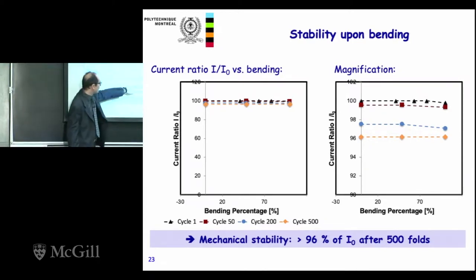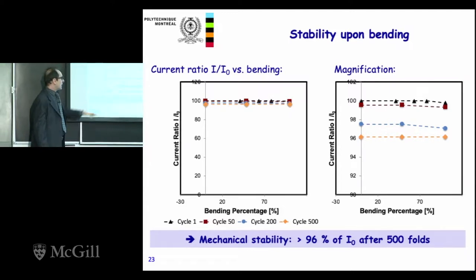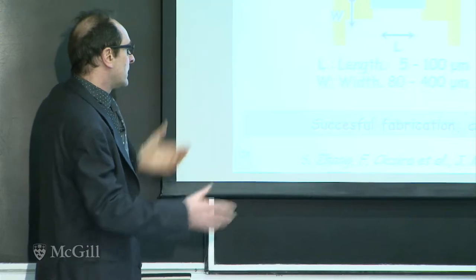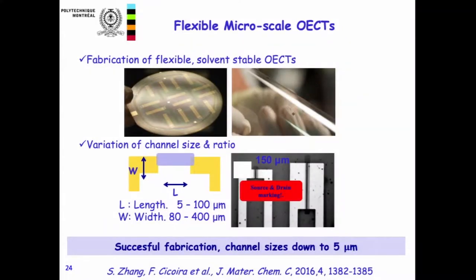Actually, this is also in function of bending percentage. Up to 70% bending, 500 times, you only lose 4% of the initial current. OK, this is, again, an example of what we have to do. So this is a two-step process. You first deposit the metal electrode, then you have to do a second process with another mask to bridge the gap with conducting polymer, and these are the results we can obtain. So we can go down to 5 microns. We cannot go below that just because we don't have the right equipment, but in principle, it's possible to go below 1 micron.